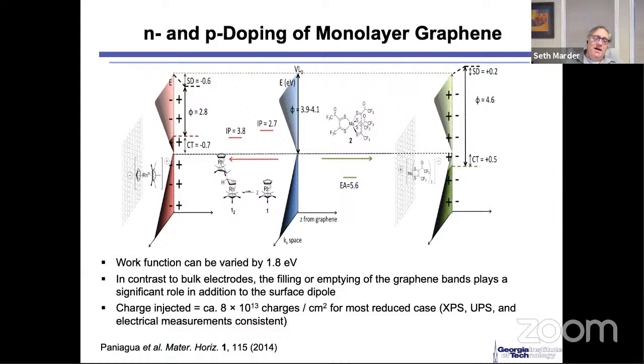And I don't believe I have the slide on Antoine's work, which, by the way, Satish, at that FPI meeting that you were at in Berlin, he reported upon. But in that work, he's shown that just by taking a monolayer of graphene and doping it with one of our n-dopants, you can make it into a very, very nice electron injecting material.